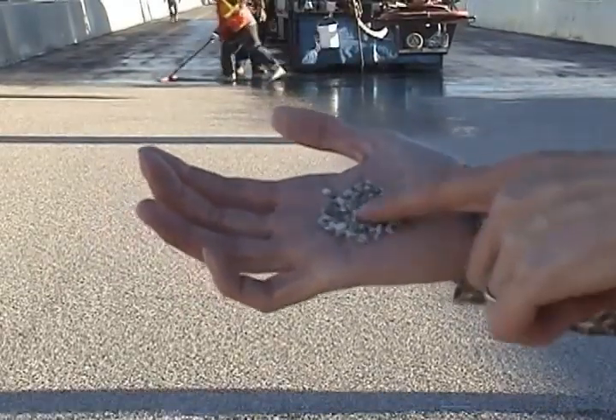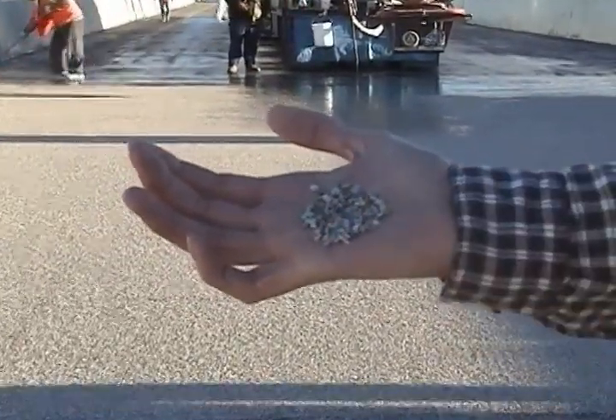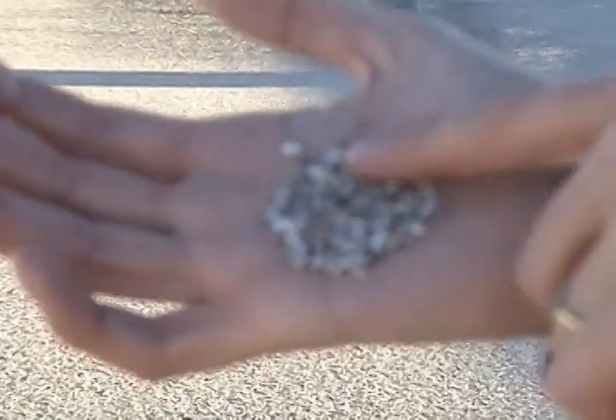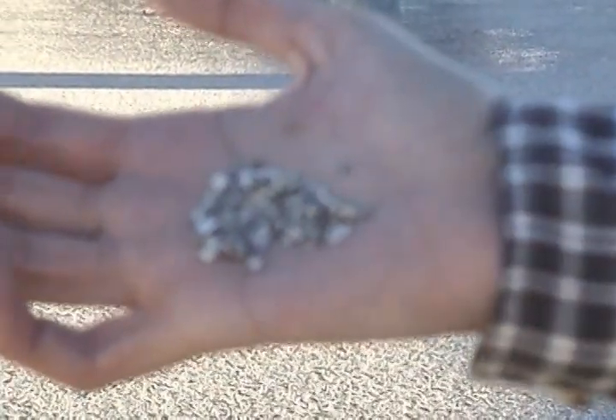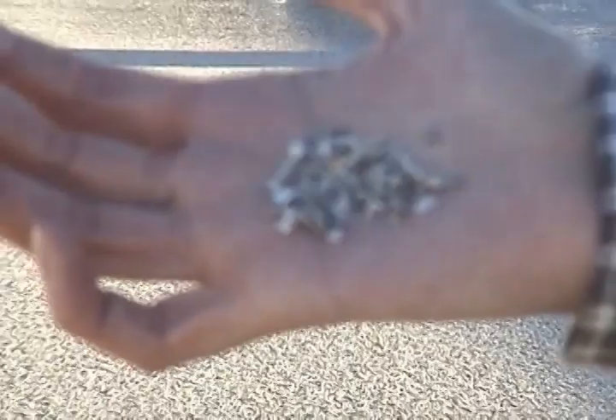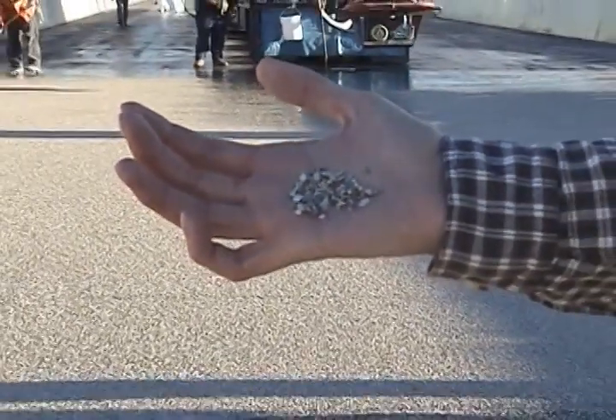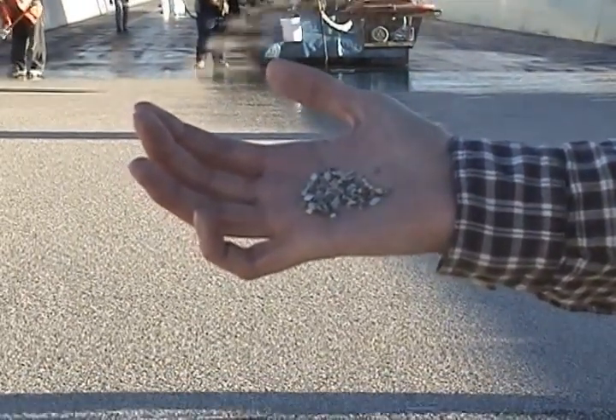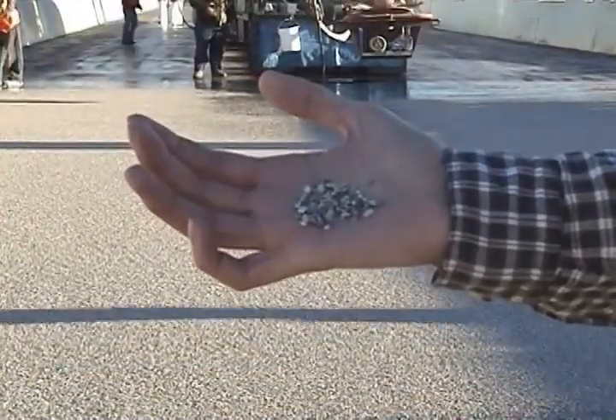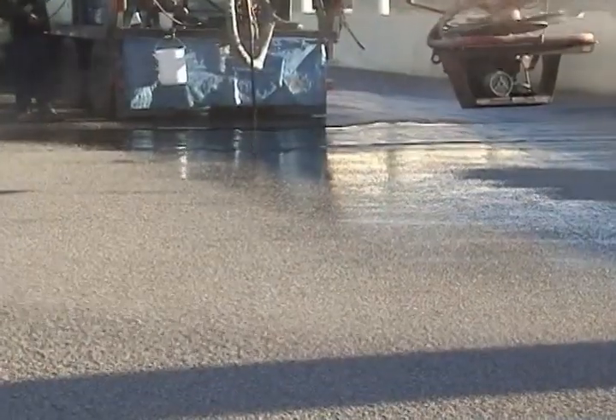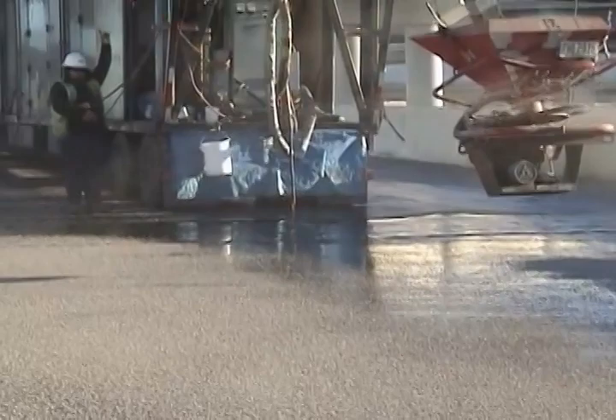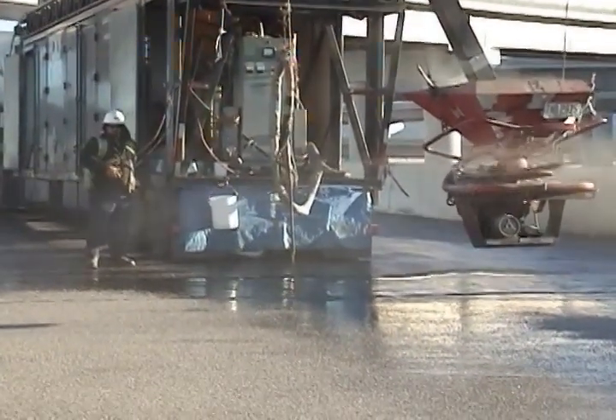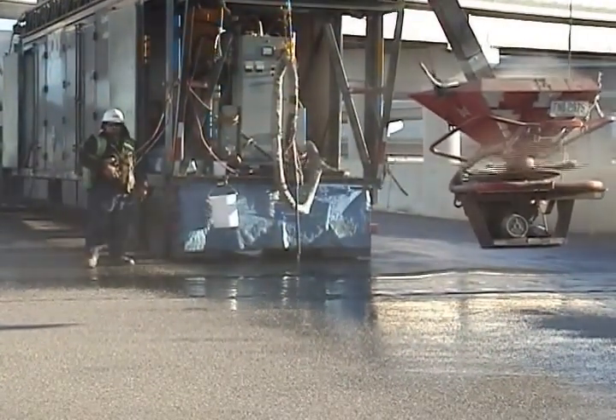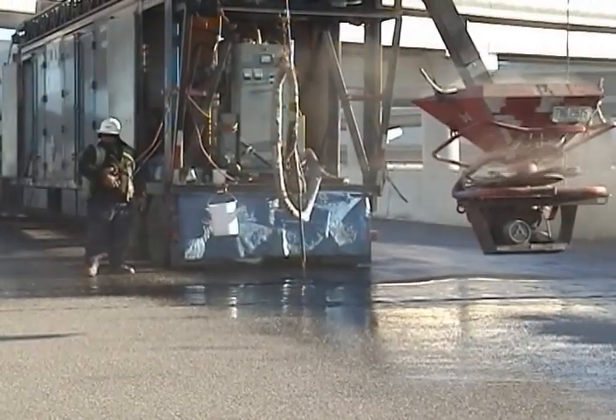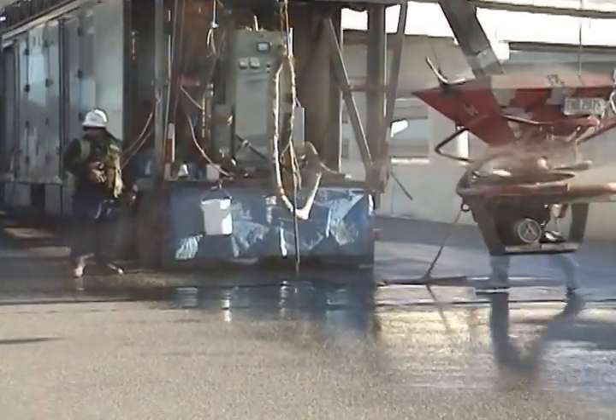The FlexoGrid is automatically mixed in the Polycarb trailer and dispensed onto the deck surface at about 100 degrees Fahrenheit. Heating the epoxy greatly increases the speed at which it will cure. Once the FlexoGrid binder hits the deck, it is immediately spread onto the deck surface using squeegees and showered with aggregates. When this layer of epoxy and aggregates has hardened, the loose material is removed and a second layer of binder and aggregates is applied. The two layers combined will have a thickness of around 5/8 of an inch.